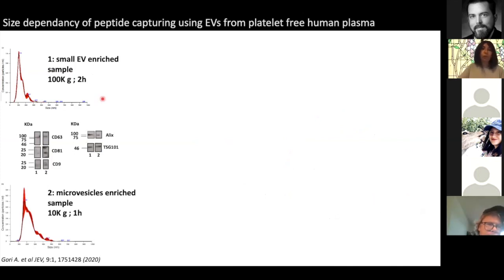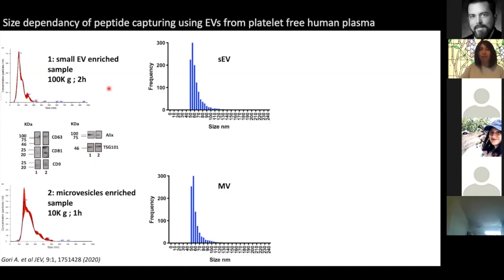The reviewer suggested to compare the binding of two samples prepared by two different ultracentrifugation protocols. So we started from an unfiltered platelet-free human plasma, and we subjected the samples to 100,000g ultracentrifugation for 2 hours to obtain a small EV enriched sample. And we subjected it to another ultracentrifugation protocol, 10,000g for 1 hour, to obtain a microvesicle enriched sample. Both samples were characterized by NTA and by Western blotting. And then these two samples were incubated on the peptide chip. And the results are the following.